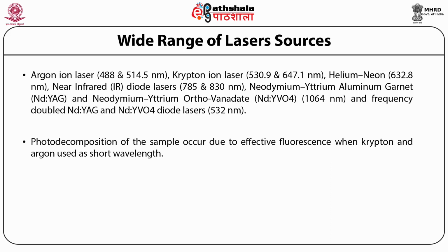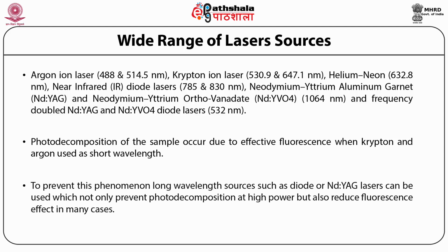Photodecomposition of the sample occurs due to effective fluorescence when krypton and argon are used as short wavelength sources. To prevent this phenomenon, long wavelength sources such as diode or neodymium, yttrium, aluminium garnet lasers can be used, which not only prevent photodecomposition at high power but also reduce the fluorescence effect in many cases.